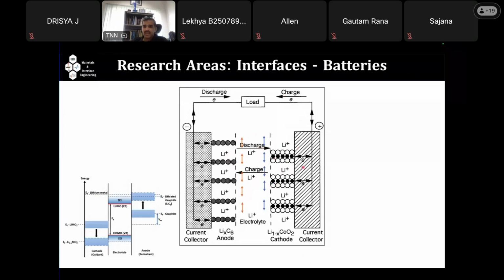while the charging process happens, you apply a negative potential to your anode and a positive potential to your cathode. So lithium ions, from the cathode, something called lithium cobalt oxide, will be de-intercalated or oxidized, and then will go to the anode, and with the electron it combines and forms an intercalated lithium compound. Lithium will form an intercalated compound in the case of a typical anode like graphite. It forms lithiated graphite or lithiated carbon system, like LiC6 kind of things.